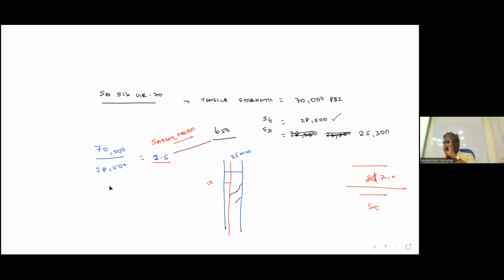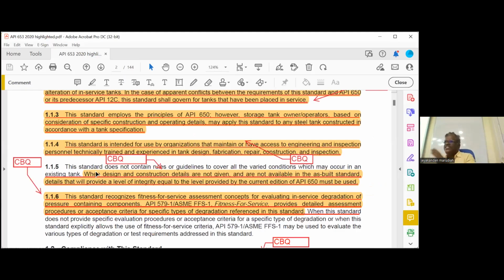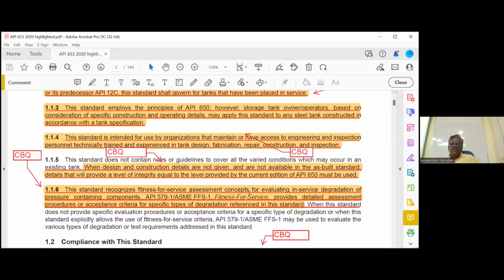Okay. There is one question: what is fitness for service? There is a methodology to analyze whether you can run with a flaw. Flaw means any defect or discontinuity detectable by NDE. Highlight this one. This standard recognizes fitness for service assessment concepts for evaluating in-service degradation of pressure containing components. API 579 fitness for service provides the detailed assessment procedure and acceptance criteria for specific types of degradation. So for each type of degradation, lamination, corrosion, pitting, crack, we have separate chapters, but 653 accepts the fitness for service.